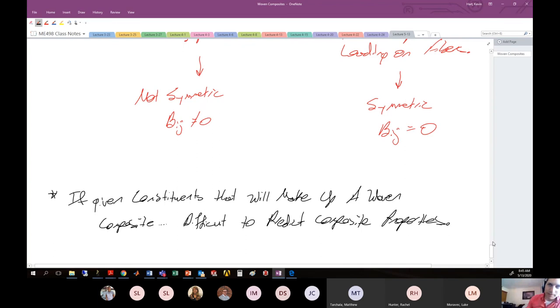So when we were talking about unidirectional composites, when we just had fibers running in one direction, if I gave you the fiber property is this, the matrix property is this, give me a prediction of what the lamina stiffness will be in the one direction and the two direction. Okay, you go to Halpin-Tsai, you go to rule of mixtures, and away you go. You can tell me what the modulus in the one and the two direction will be. Fine, no problem. You cannot do that with woven composites because there is an additional fudge factor that comes in because of the way that the structure is woven together.